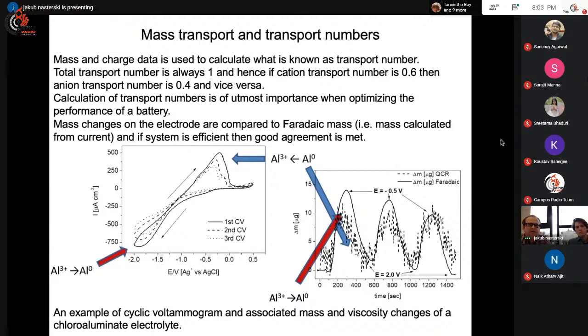So Faradaic mass is not something that was measured. This is mass calculated purely from the current. This is under the assumption that your electrochemical reaction is 100% efficient. And you can see that for this particular system, almost all of the electrical energy was converted into mass changes. You can see in the last cycle, the agreement is almost perfect. And pretty much entire electrical energy was used to contribute to mass changes.